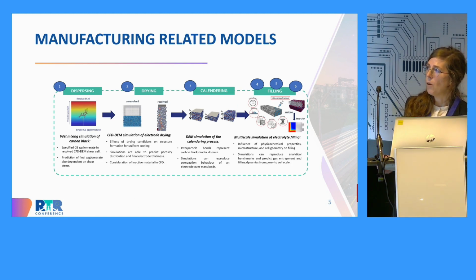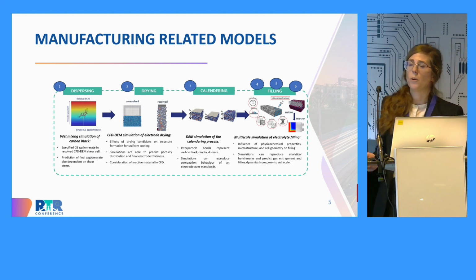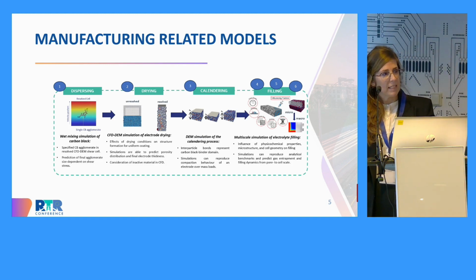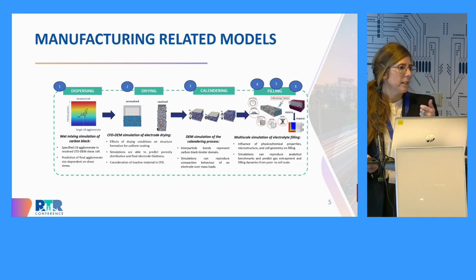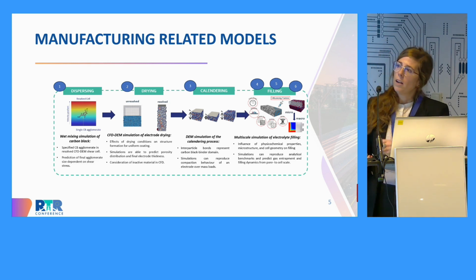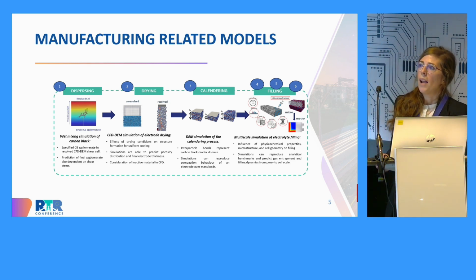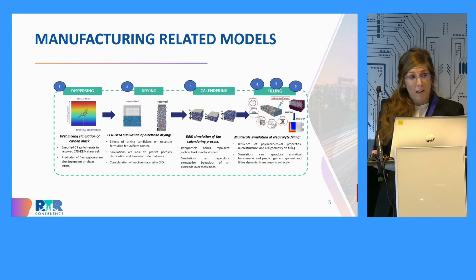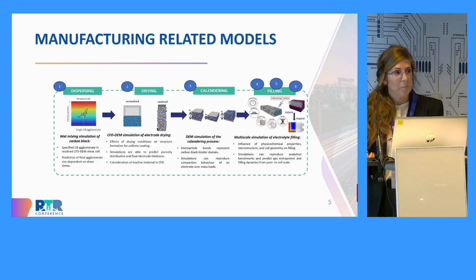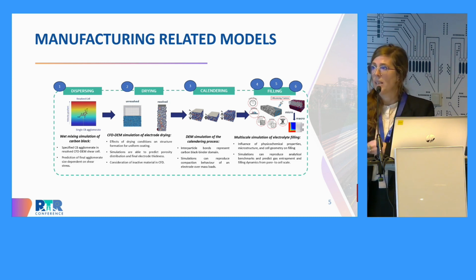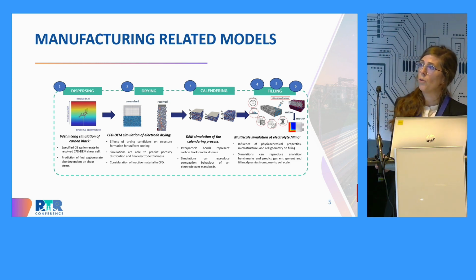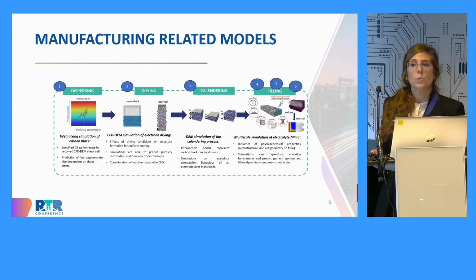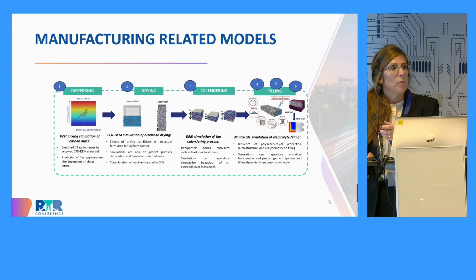So I'm now focusing on electrode fabrication, and we were focusing on the mixing, drying, and calendaring. And then from this approach that was developed by a partner, a DEM approach combined with fluid dynamics software, we're able to identify which are the best parameters for achieving certain properties. So for instance, in the dispersion or mixing process, they were able to predict certain rheology properties depending on the agglomeration of the